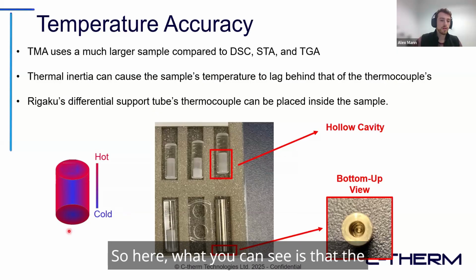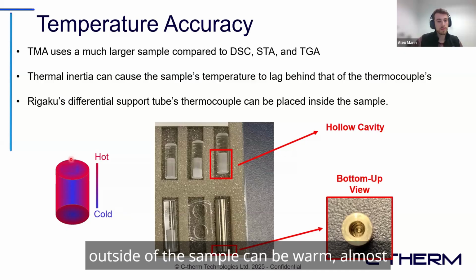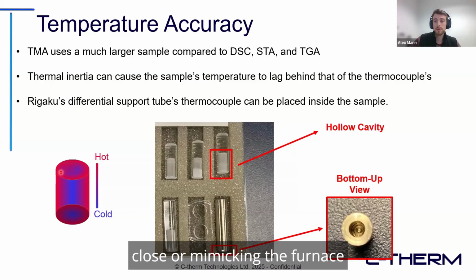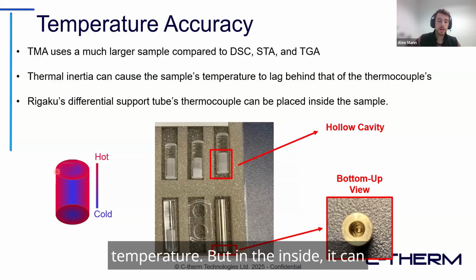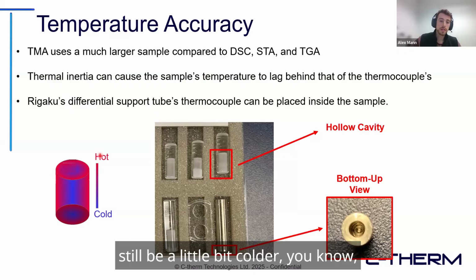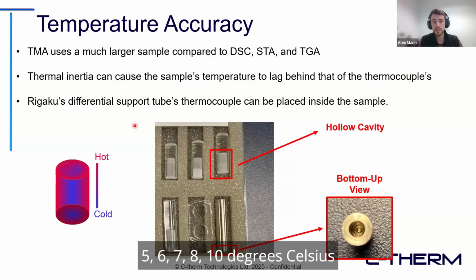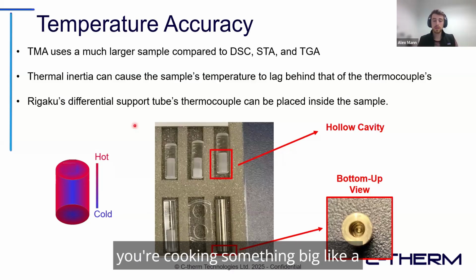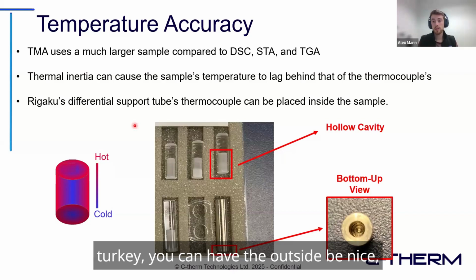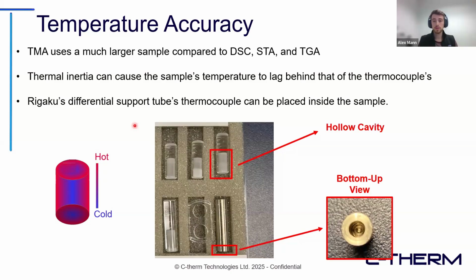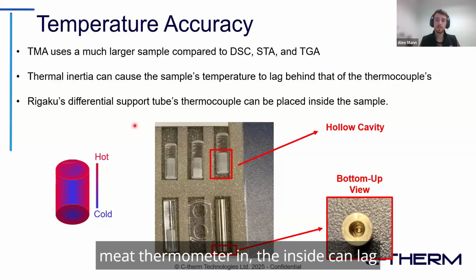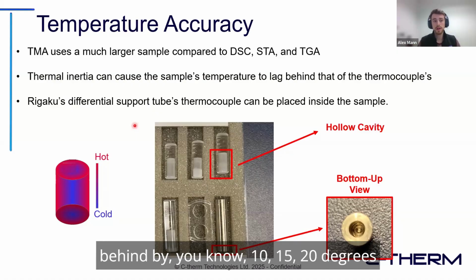So here, what you can see is that the outside of the sample can be warm, almost close to or mimicking the furnace temperature, but on the inside, it can still be a little bit colder, 5, 6, 7, 8, 10 degrees Celsius behind. I like to think of it as when you're cooking something big like a turkey, you can have the outside be nice, crispy, warm, but when you stick your meat thermometer in, the inside can lag behind by 10, 15, 20 degrees Celsius.